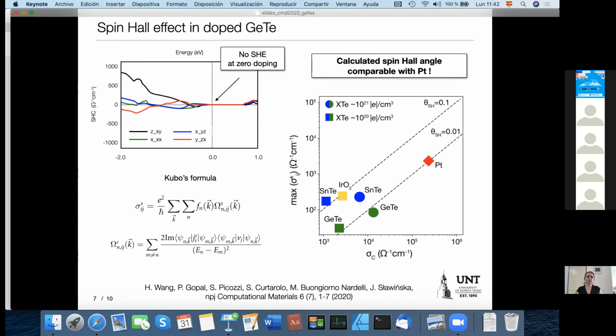It is also not so difficult to include the doping in the calculations. And of course, we can calculate in the same way the spin Hall effect for doped systems. Here I have presented the results of the spin Hall angle calculated for germanium telluride doped with different concentrations, for example, in the range of 10^20 holes per cubic centimeter or larger, 10^21. Actually, this one is closer to experiment. And it is easy to notice that the spin Hall angle is close to the one of platinum. So it looks quite promising.